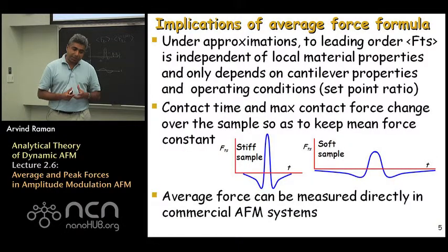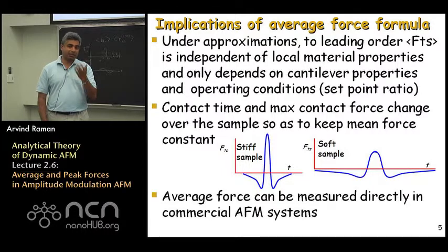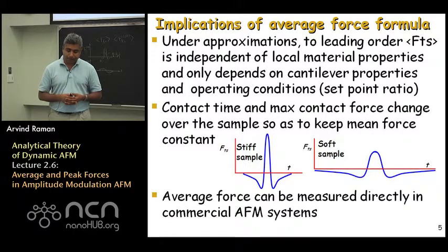When we start looking at peak forces, we'll see that this tendency becomes quite different. So the implications of this result are that, at least to first order, when one tries to describe the leading order effects of average forces and its connections to local properties, the average forces tend not to depend on local properties, but rather depend just on the cantilever and the operating conditions at which you operate the microscope. So this brings us to an interesting question as to